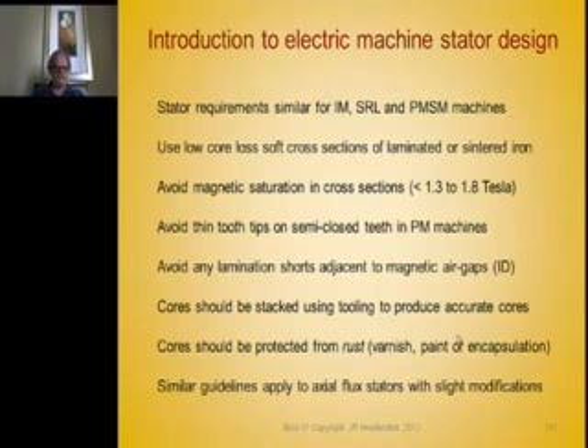This means around between 1 and 1.4 Tesla. Try to avoid going up as high as 1.8. Now, thin tooth tips on the stator teeth. All these stators are open slot stators, and one of the problems with trying to use the same induction stator lam with a PM machine is that those tooth tips saturate very quickly, which increases the cogging torque.